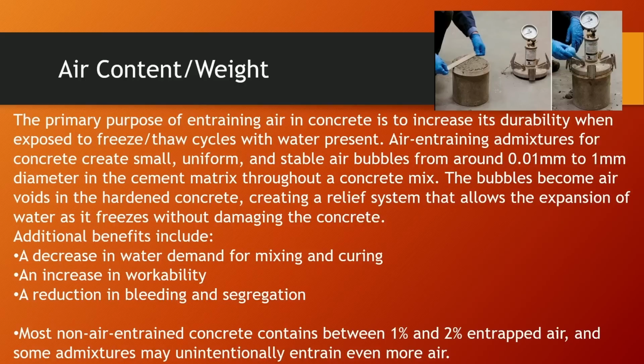The bubbles become air voids in the hardened concrete, and they create a relief system, kind of like a cushion system, that's going to allow the expansion of water as it freezes without damaging or cracking the concrete. Additional benefits include a decrease in water demand for mixing and curing, an increase in workability, and a reduction in bleeding and segregation. So that's really why you like to have air and what air does in the mix.